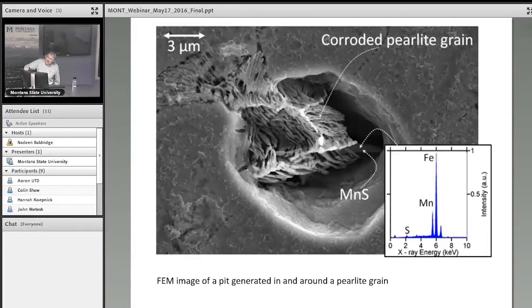But the point of this is that if you look at this spectrum I took from this manganese sulfide, you see the manganese here, and you see the sulfur peak. The sulfur peak is now very small. This will happen to you when you do analysis. You say, my low energy X-ray peaks don't look as good as they should. Well, here's an example. The reason is very simple: you are in a hole. My detector is up here towards this corner. These are low energy X-rays. For them to go to the detector, they have to go through this wall of iron and get absorbed. Absorption is not uniform. The high energy manganese K alpha peak goes through a bit faster, with less absorption. So you see a bit bigger of this and less of this; it will happen to you more often than not. So you just have to be very careful with that.